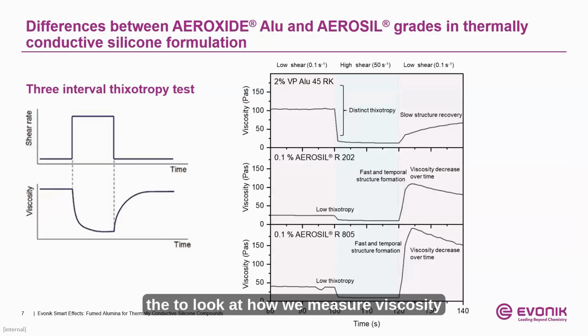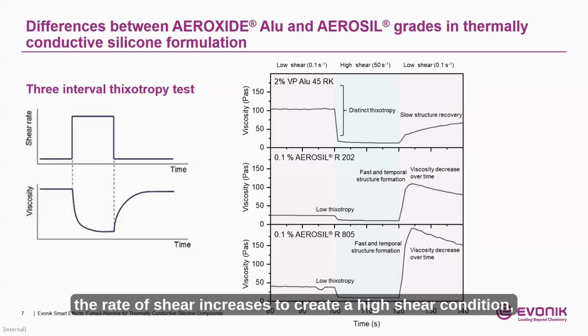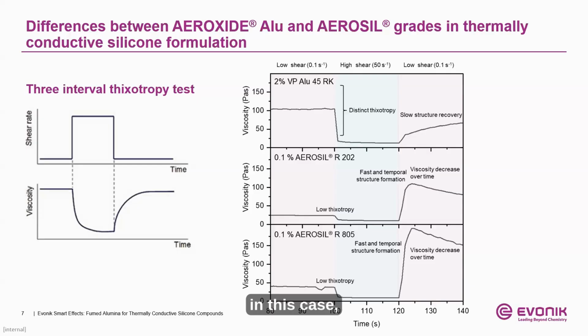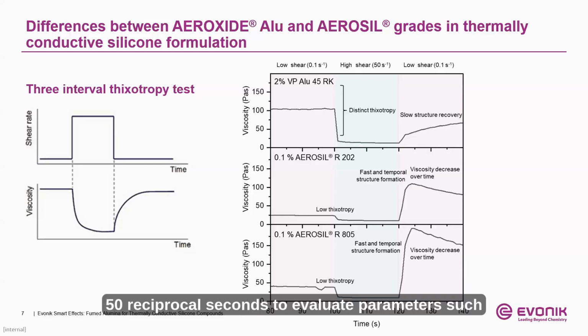So to look at how we measure viscosity, we rely on a rheological measurement known as the 3ITT, which is a 3-interval thixotropy test. The test begins at low shear conditions, typically, at least in this case, 0.1 reciprocal seconds of shear rate to establish a baseline viscosity of the formulated product. From there, the rate of shear increases to create a high shear condition, in this case, 50 reciprocal seconds, to evaluate parameters such as the shear thinning behavior of the material and the lowest viscosity possible for the product while undergoing these intense shear conditions.